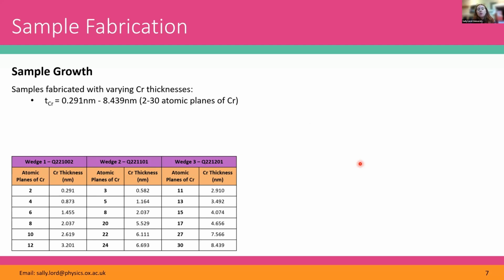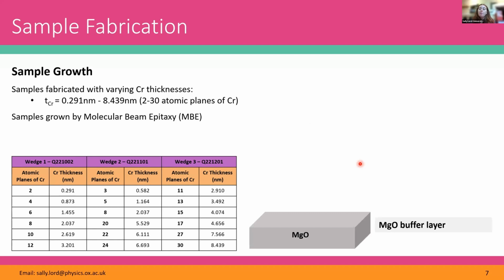And the reason that we were interested in varying the chromium thickness is because it's this interlayer thickness that determines the magnetic properties of the trilayers. So the samples were grown by molecular beam epitaxy. And first, a buffer layer was deposited on the MgO substrate to provide a homogeneous surface.